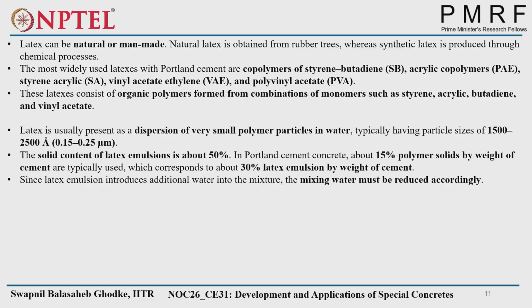The main thing is that latex is usually present as a dispersion of very small polymers in water. It is a solution where the small polymer particles have a size in the range of 1500 to 2500 angstrom, that is 0.15 to 0.25 micrometer. These small polymer particles disperse into the water. So how much? The solid content of latex emulsion is about 50%, meaning 50% is water and 50% is polymers. That is the content of the latex.